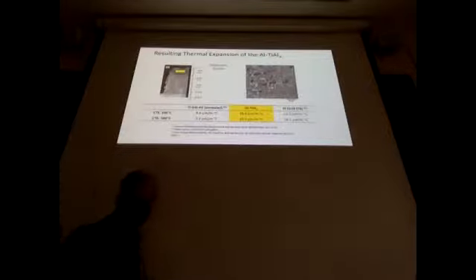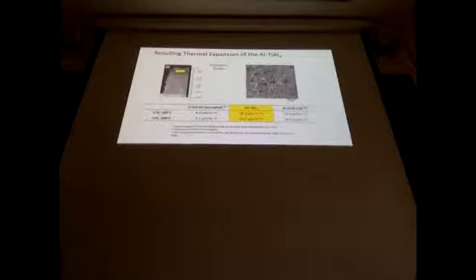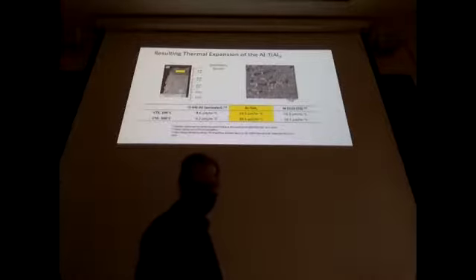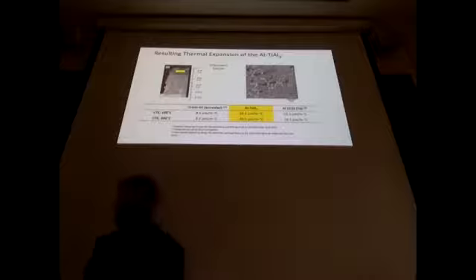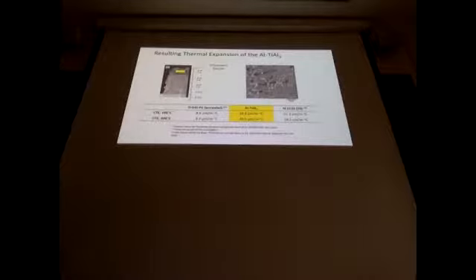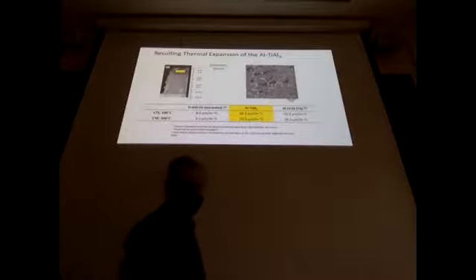And then just to test how good we are, which this is our failure, I'm afraid, we took a dilatometry sample from the material that we made. We ran it and compared it to Ti-64, which is what we were trying to get to. So our thermal expansion for Ti-64 is roughly about 9 microns per meter per degree Celsius. And then here's our 2219 that we used on the other side. We were able to reduce it a little bit, but we're nowhere near where we would like to be. So although we were able to use that titanium aluminide to get the thermal expansion coefficient down a little bit, it wasn't really enough for what Sandia was looking for. But with that said, maybe we can try to modify both sides, titanium as well.